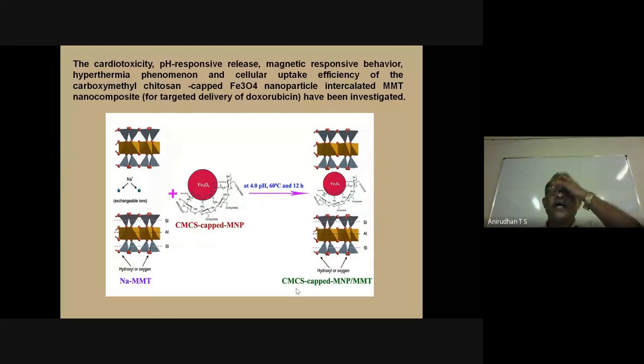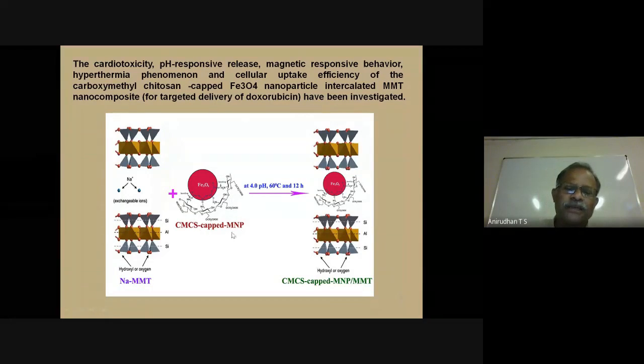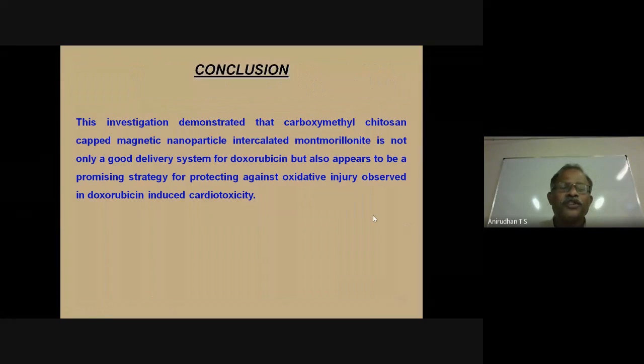And second, another material: we can introduce doxorubicin as an anti-cancer drug into this layer structure after treating with carboxymethyl chitosan. So just remember this again. Chitosan is converted into carboxymethyl chitosan capped with magnetic nanoparticles, and this involves 2-3 steps. And after preparing this CMCS capped MNP, we have introduced this product inside the interlayer cavities of these clay minerals.